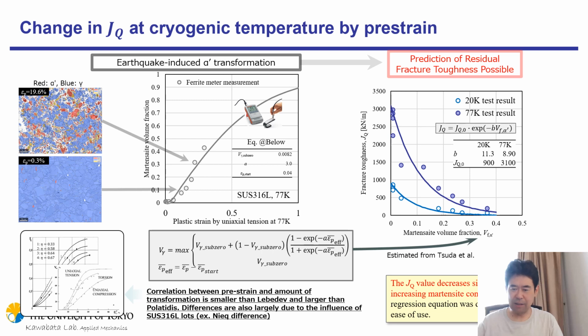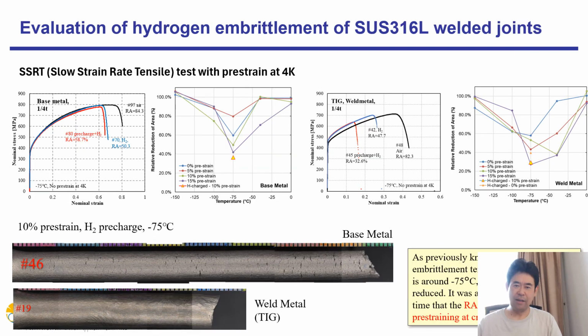So if the martensite volume fraction is, for example, 10%, the remaining fracture toughness can be predicted by this curve. And fracture study should be done based on this degradation curve. Hydrogen embrittlement. This is another topic.